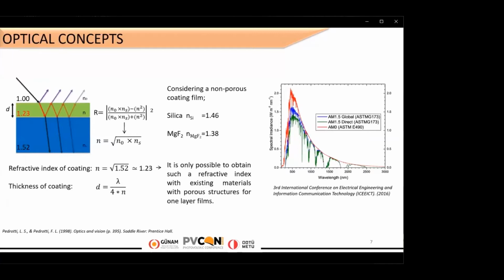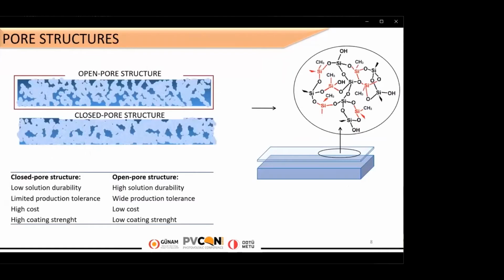Among the existing materials, there is no coating material with a refractive index of 1.23, so we have to obtain a porous film to decrease refractive index. Pore structures can be open or closed types. You can see on the table that there are advantages and some disadvantages compared to each other. We try to eliminate low strength of open structure by chemical modification. You can see in the schematic view of molecules on the right corner side of the page.